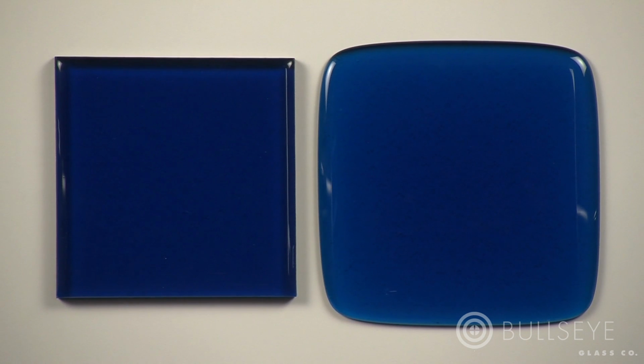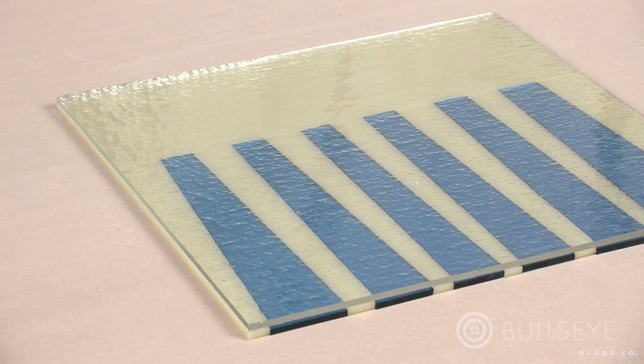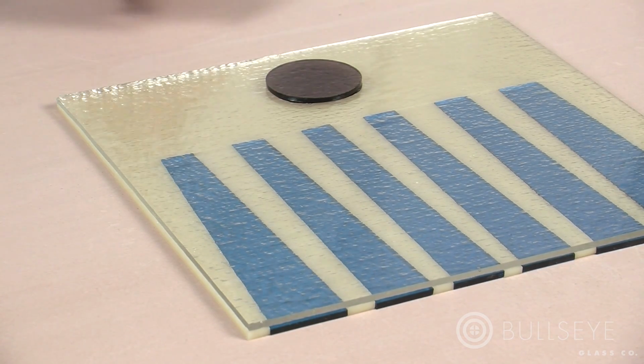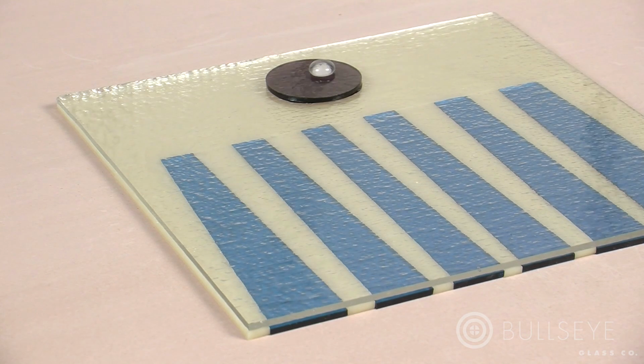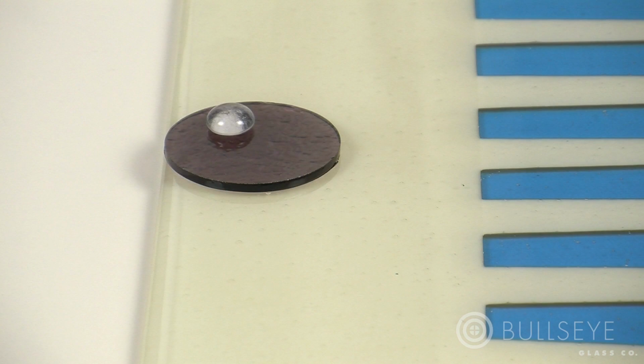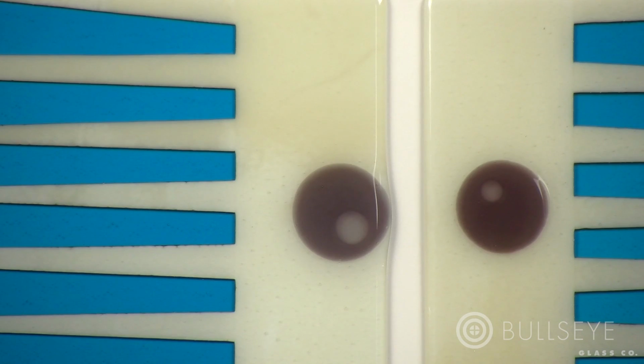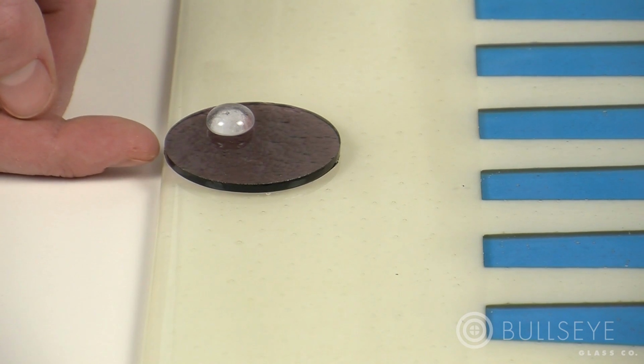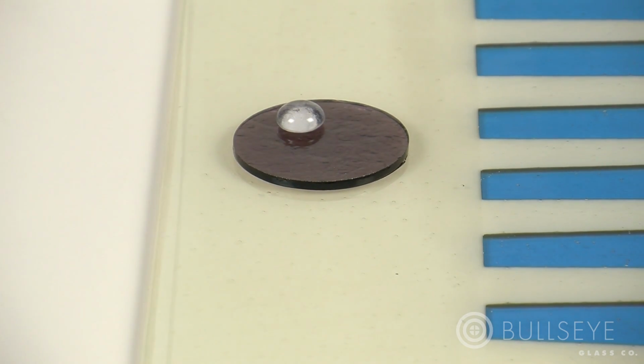Both methods of firing thicker pieces are valid. They simply yield very different results. Applying small pieces of cut sheet glass, frit, powder, or stringer to the top surface of a 6mm base allows you to extend the design possibilities. But if too much glass is added, or it is placed too close to the edge, it may flow out and distort the footprint of the finished piece, if not contained within dams. While this type of distortion can be a design feature, it may not be what you desire. To limit such distortion, keep material added to the top surface at least 3/4 of an inch from the perimeter, or dam the piece.